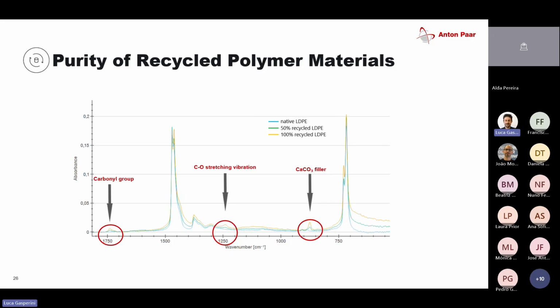So why is the carbonyl group of importance? Hydrocarbons all have the carbonyl group, which tends to oxidize. So by an increase on this peak, you can tell how old it is, or you can actually tell if it's a recycled polymer or not. This is typically used in the oil and gas industry, for example, when you look at lubricants. If you think about the lubricants in your car, how do I know when the lubricant is already used up? Typically you do a viscosity measurement, but the problem with the viscosity measurement is that it's already too late.